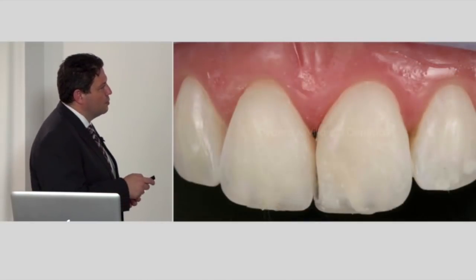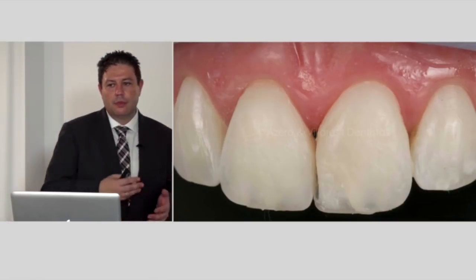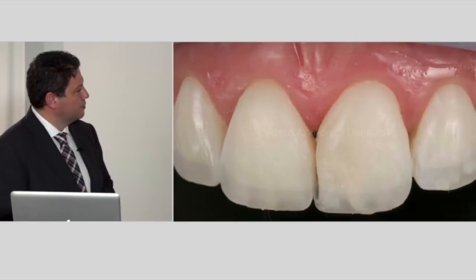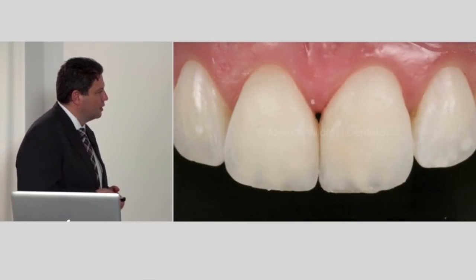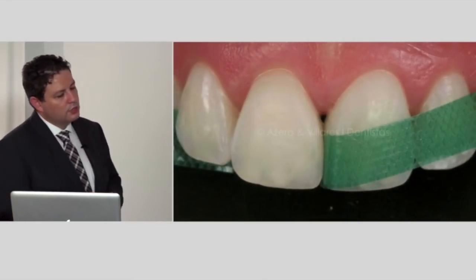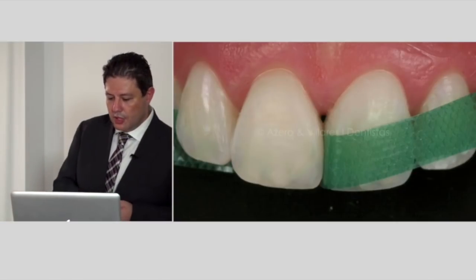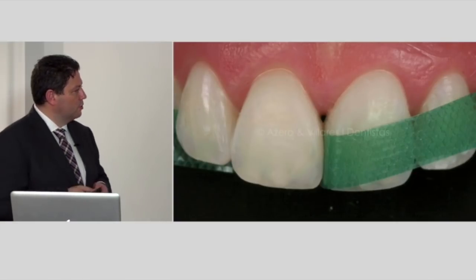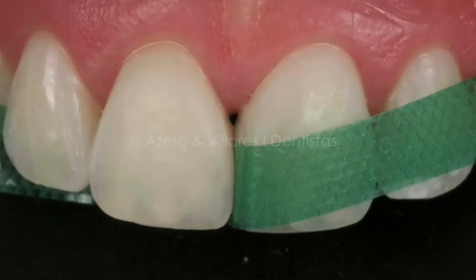In this case, we modify the emergence profile with a metal matrix. Then we use this type of strips to polish the interproximal part. These are the Epitex ones. The advantage that they have is that they don't eliminate too much of the anatomy of the teeth, that we make at a very slow speed to have a very good shape.